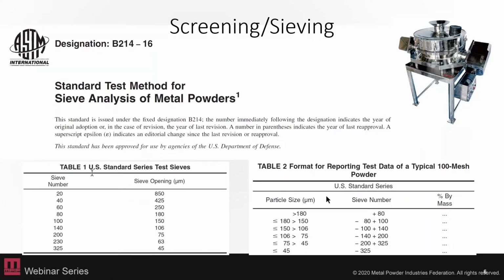Again, screening and sieving has been around for a long time, and it is correlated back to the aggregate and construction industry. But when we're looking at metal powder specifically, the ASTM B214-16 is the method that you want to follow, and this is just the high level of the test sieves that you can use, as well as what those sieve numbers and particle sizes correlate to. So a lot of times when you're getting a powder or ordering a powder or producing a powder, these are the certifications that you're going to use when advertising that powder or certifying that powder.